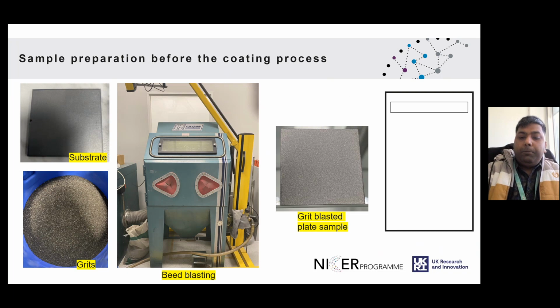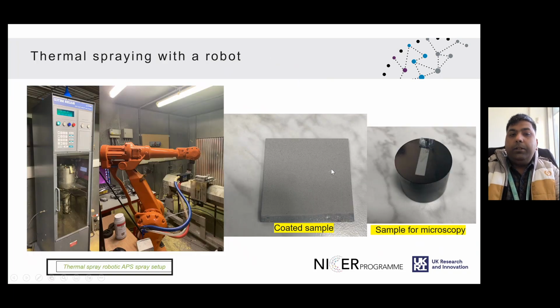After it has been grit blasted, it has achieved some artificial roughness, and it is now ready to receive the coating. In order to perform the coating, we then take this substrate, the grit blasted sample, to the coating chamber, which is where the magic happens. So through this plasma spray gun, our aim is to feed the powder over here with the powder feeder unit. And this robot can be programmed with the right selection of the gas and the gas feeder unit on the control unit, which then allows us to spray this particular coating from the gun. And you then receive a coating on the sample, which could be a certain micron thickness.